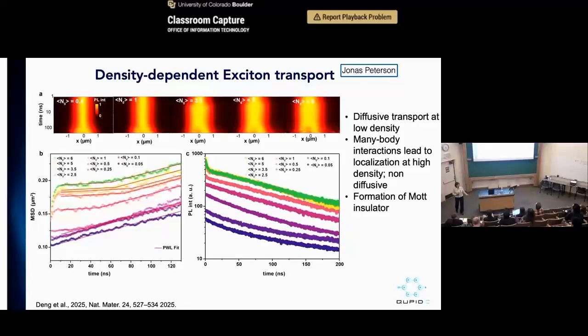And so in order to know whether or not we actually realize an exciton Mott insulator, what we're going to look at is whether or not the exciton distribution at high density becomes pancake-like, right? Also whether the exciton motion would stop, because that's what Mott insulators would tell you as you enter the Mott regime. So to do that, we do this measurement of looking at the emission. This is actually PL imaging, so this is lifetime on one axis and space on the other axis, as a function of exciton density. What we plot here is the mean square displacement of the exciton as a function of time and as a function of exciton density. Oh, yeah, I should mention all these measurements are at 4 Kelvin.